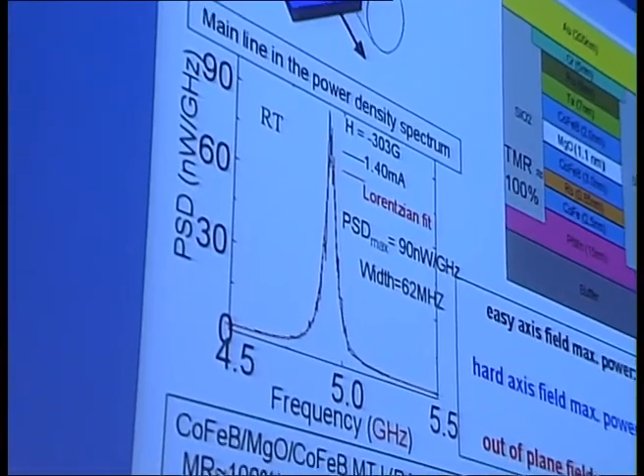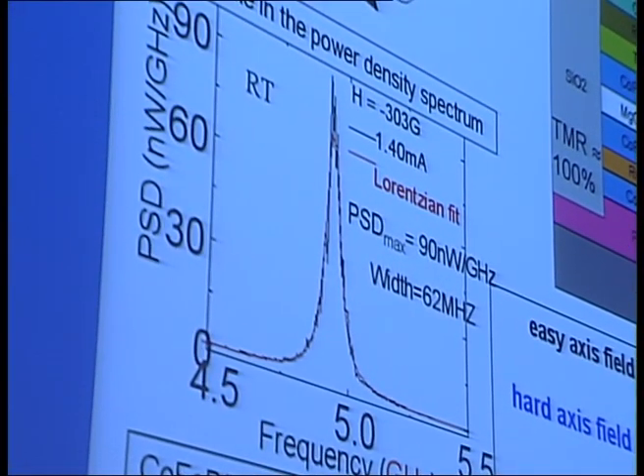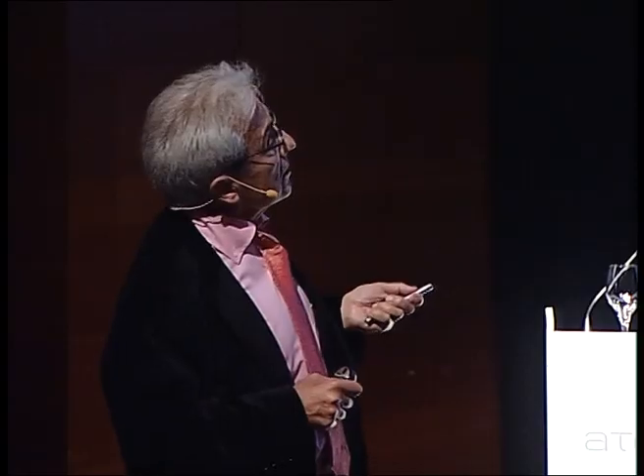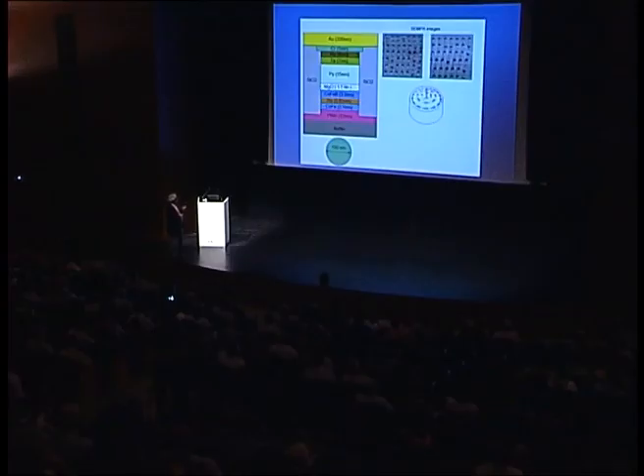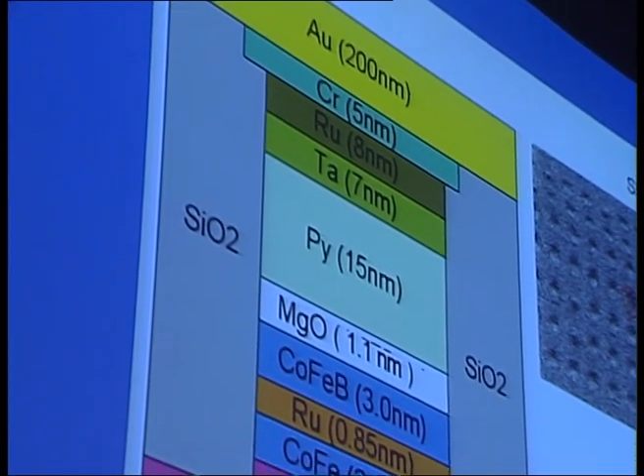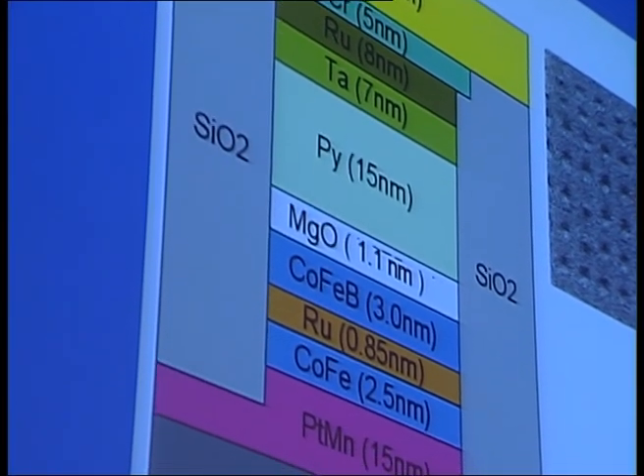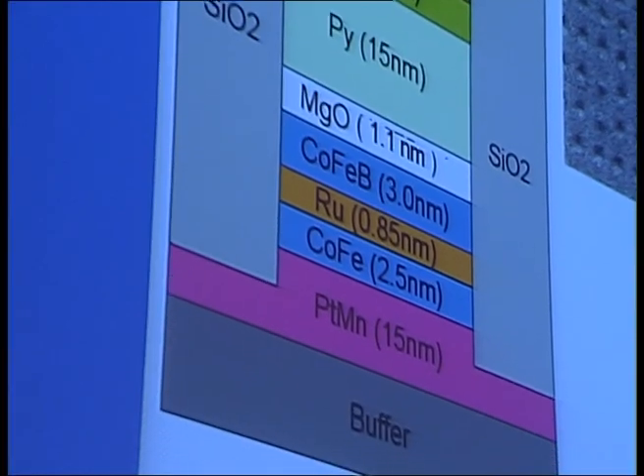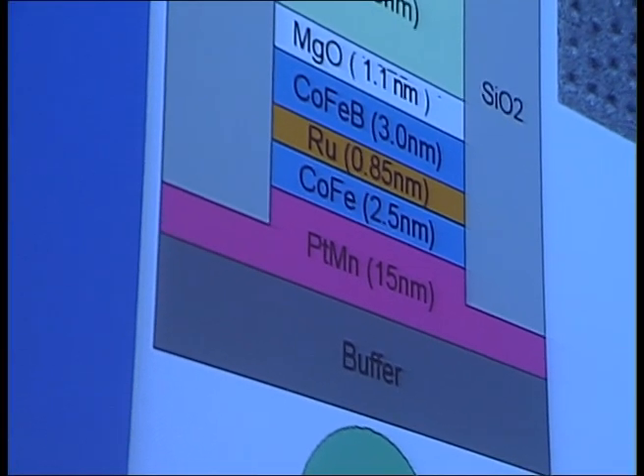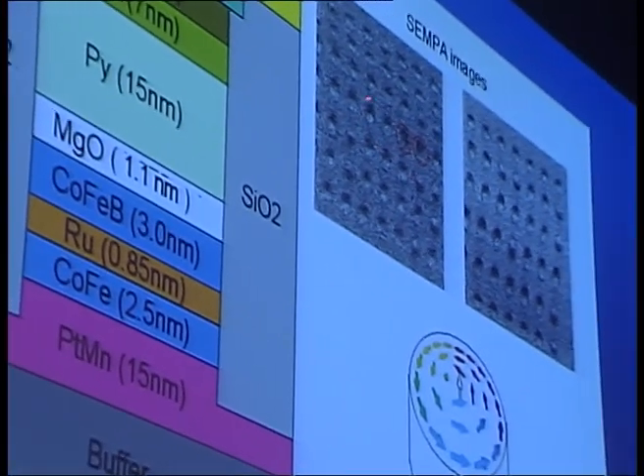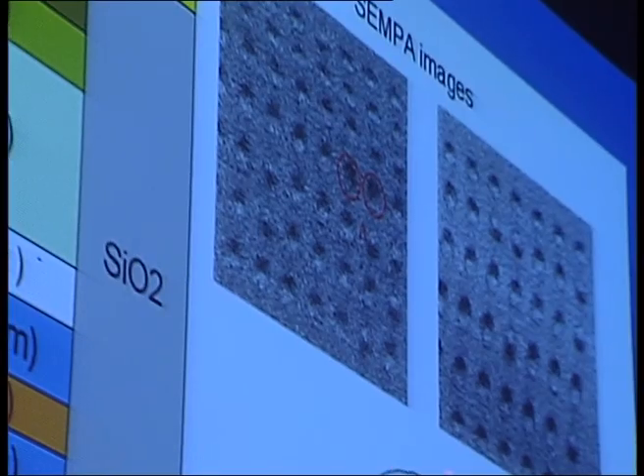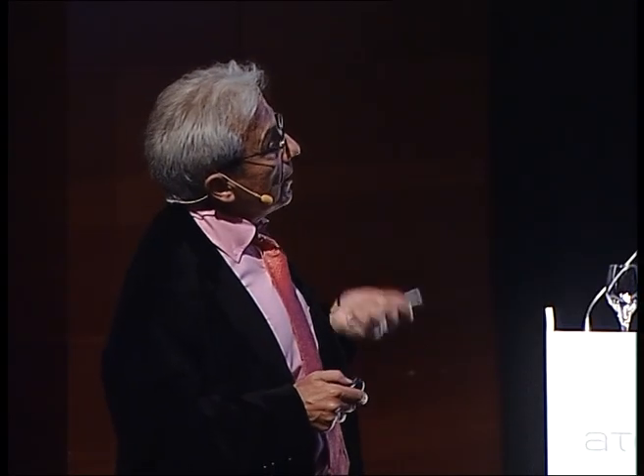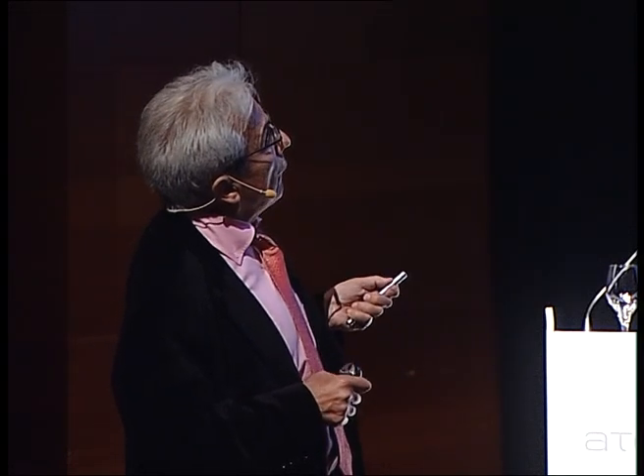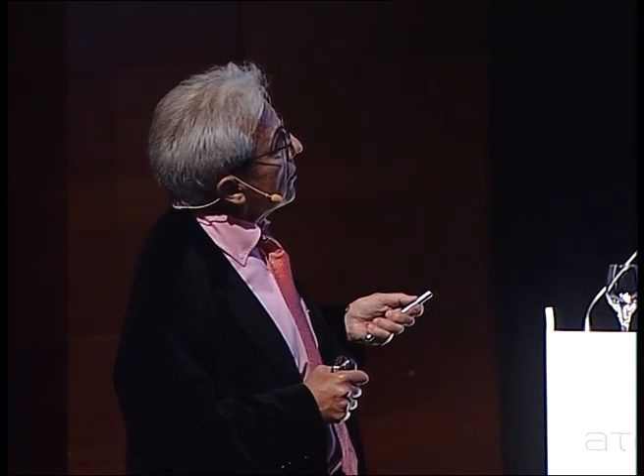But in fact, there are other ways to produce microwave oscillation, not with precession but with the rotation of magnetic vortices. We obtain this in this type of tunnel junction, where now the free layer is thick enough to stabilize a vortex configuration. This is a vortex configuration of the magnetization, where there is no pole, no magnetic charge at the surface. You can see a sample image revealing, from the succession of black, gray, and white, this rotation of the magnetization around the dot. And what can be done by spin transfer is a sort of rotation of the core of these vortices in this way.